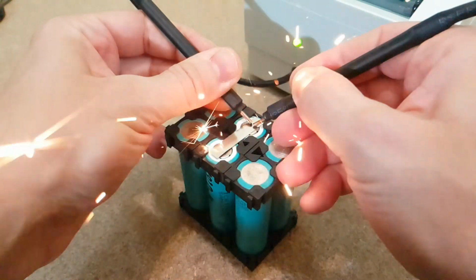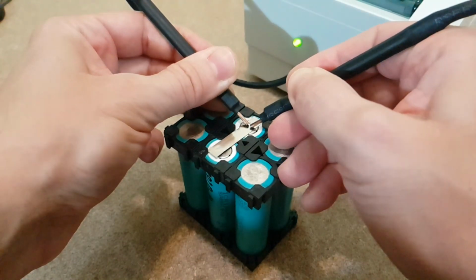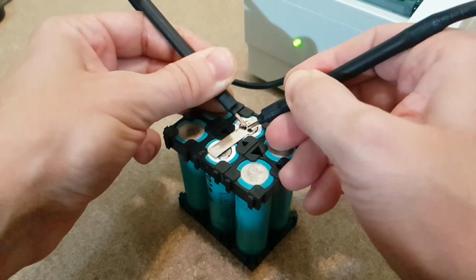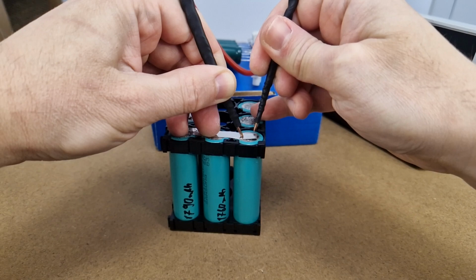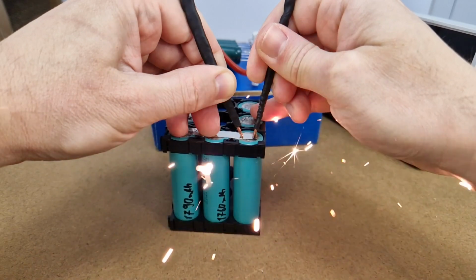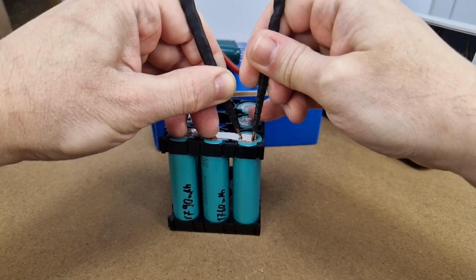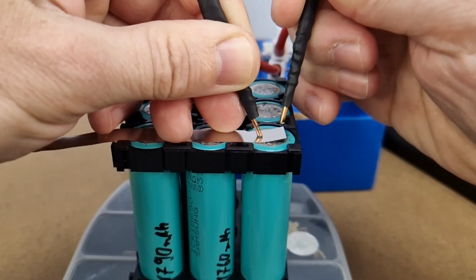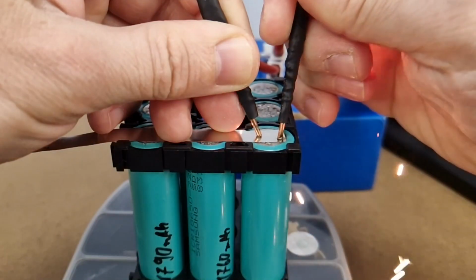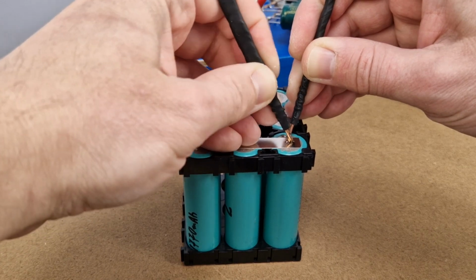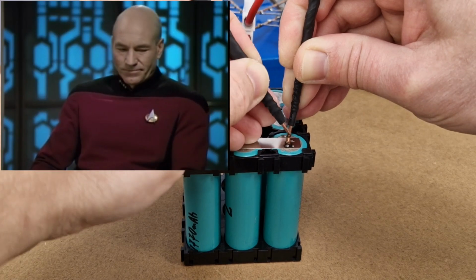In a typical welding circuit with MOSFETs or even with a solenoid switch, you can press hard on the nickel strip with both electrodes and then the current will flow and melt the contact points between the strip and the cell housing. But without being able to control when the current should flow, the capacitors will completely discharge when you touch the nickel strip. And if the nickel strip is not pressed with both electrodes, it will melt right before it touches the battery. I need to move faster than the current flow. And after more practice, I became Captain Current and can finally move fast enough to get some better results.